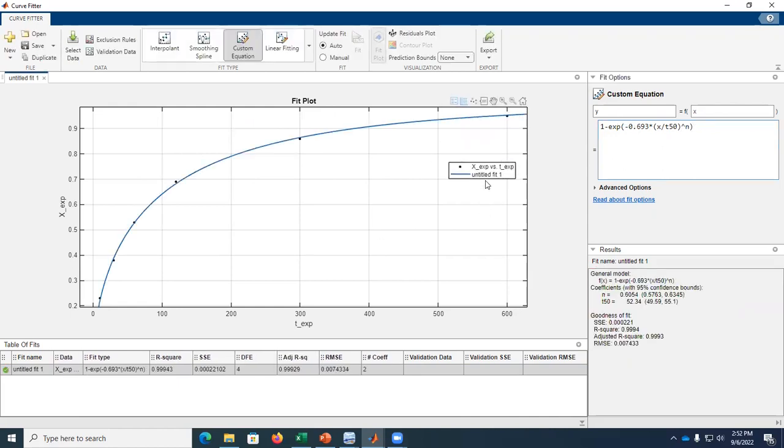So, in this case, fortunately, depending on your machine, it could just automatically detect the parameters. Here in this case, it will automatically detect. So you see N was selected as 0.6 and T50 as 52. So those are the parameters that fit the model pretty well.